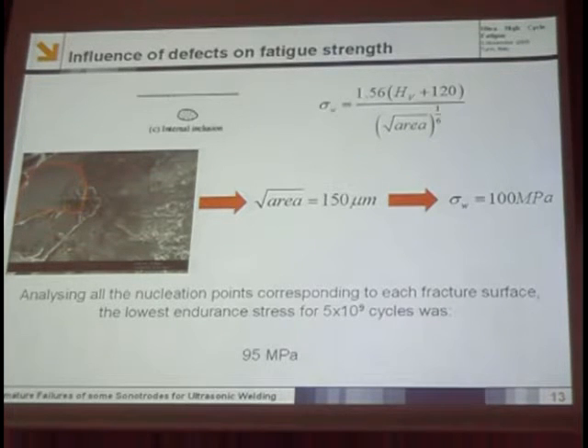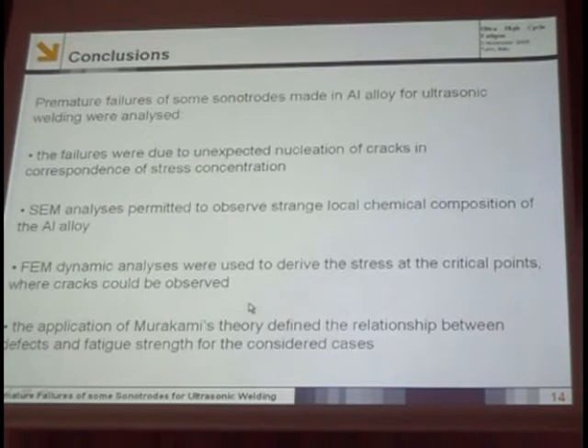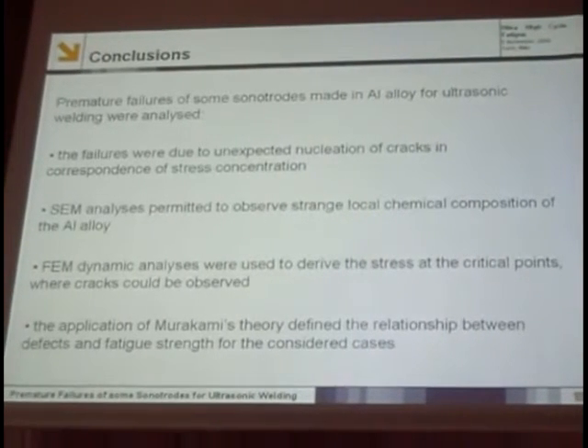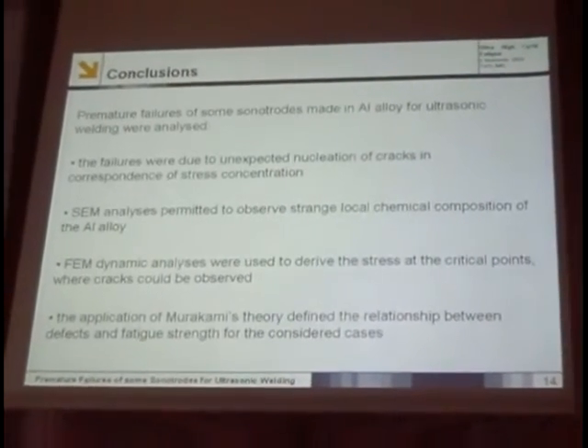First, I want to repeat that the finite element analysis was perhaps too conservative, but I think that with a good modelization of the system, the values of the maximum von Mises stress should be higher, still higher than this endurance limit. So to conclude, we analyzed the premature failures of some sonotrodes made in 7075 alloy.